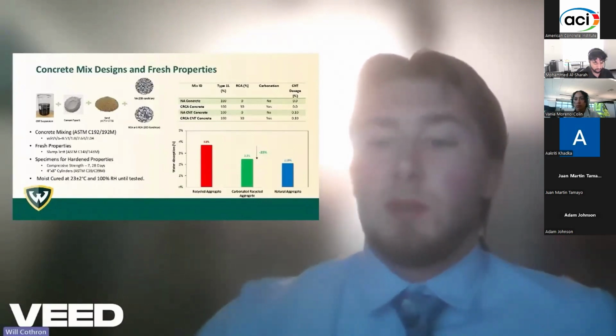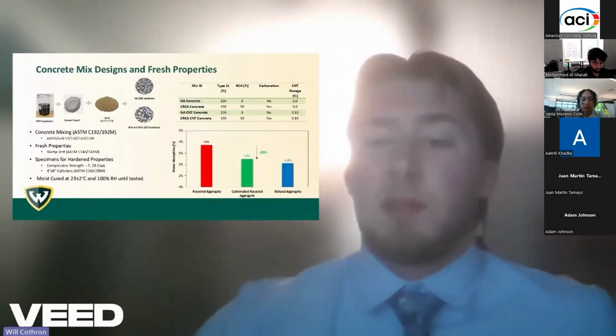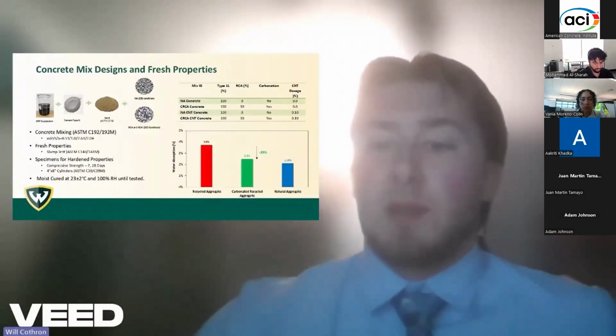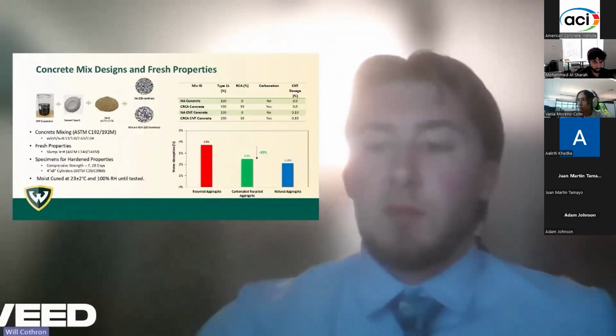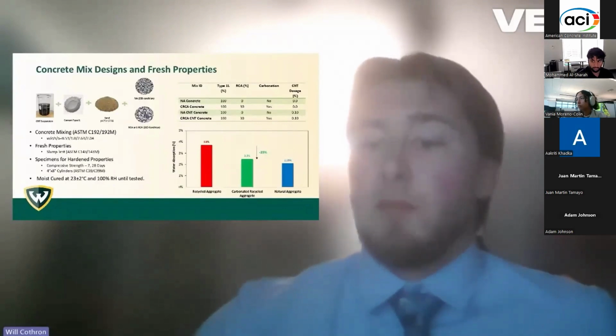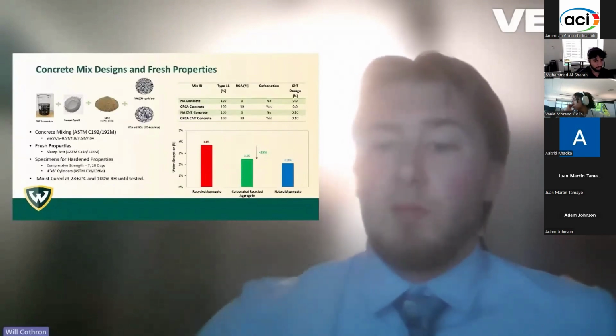Each mix used cement type 1L standard cement, natural aggregates or recycled concrete aggregates, both in saturated surface dry conditions, and carbon nanotube suspension when applicable. The exact proportions of water, cement, sand, and aggregate used were maintained at a ratio of 0.51, 1, 2.63, and 2.04 to ensure consistency and comparability.